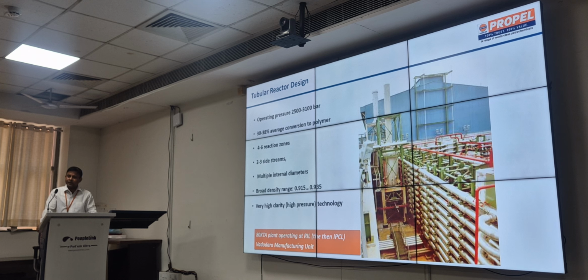Tubular reactors also operate at much higher pressure, 3,000 to 4,500 bar. Conversion is slightly better than autoclave, 30 to 38%. The reaction zones are 4 to 6, with multiple internal diameters, and the density range we can achieve is 915 to 935. So Reliance currently, earlier the IPCL plant, now has this.